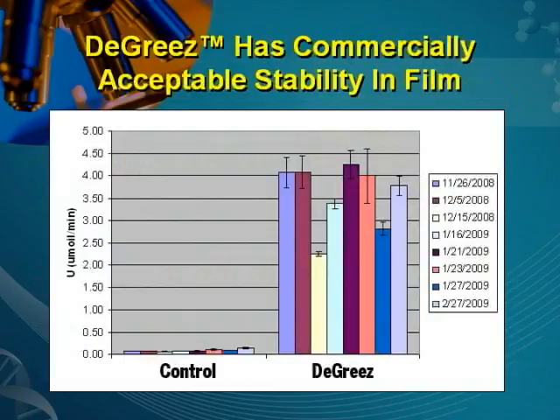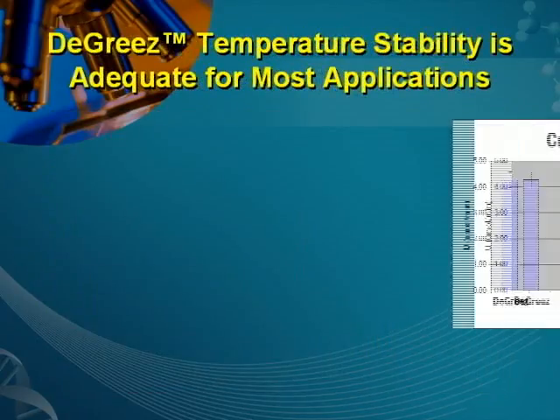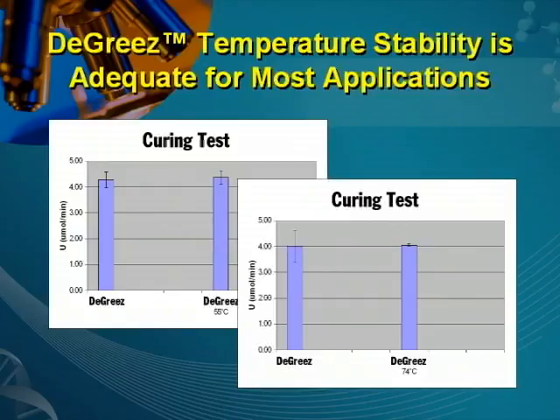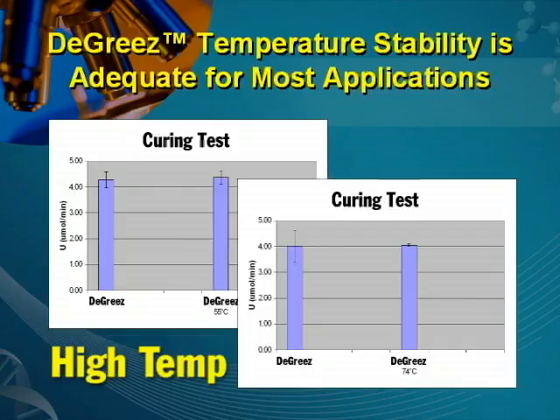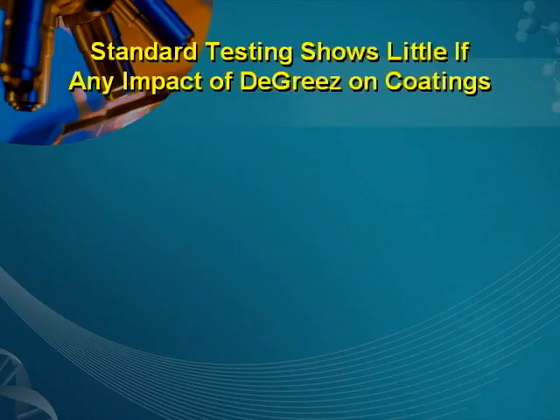It also has been shown to have commercially reasonable stability when formulated into coatings and stored on the shelf. The temperature stability of DeGreez is adequate for most commercial applications and formulation protocols. These studies include extensive elevated temperature studies showing the ability for DeGreez to withstand high temperature curing as well as UV curing processes. Standard testing shows little if any impact of addition of DeGreez on coatings.